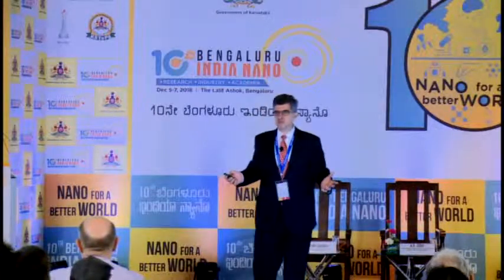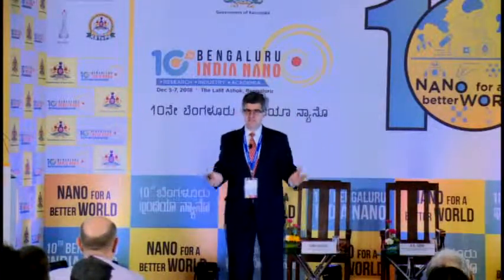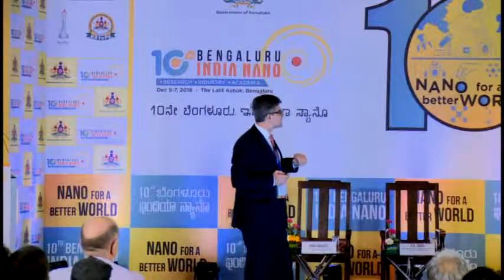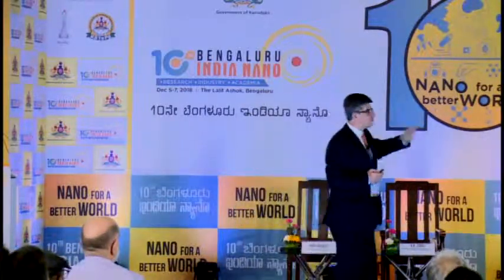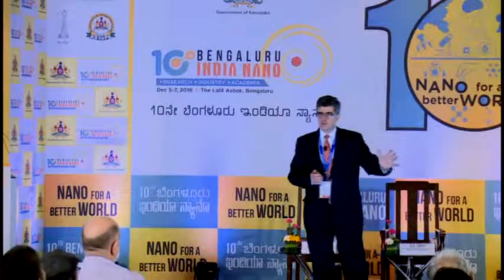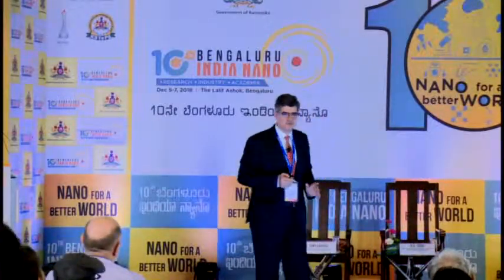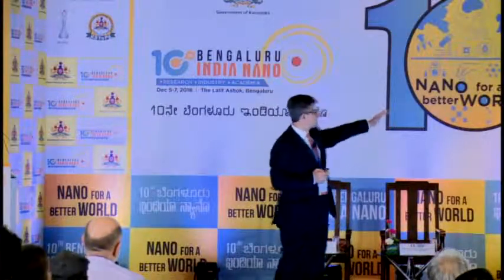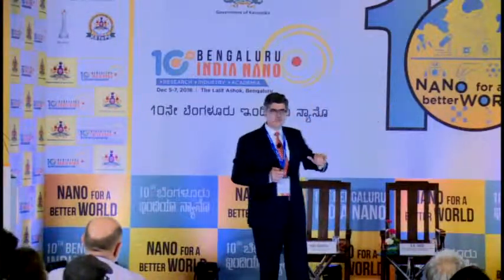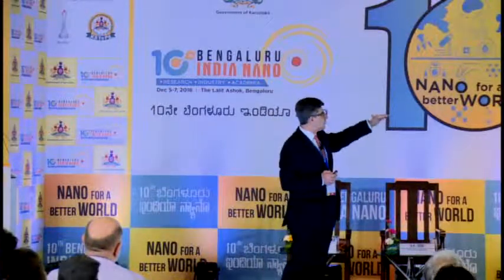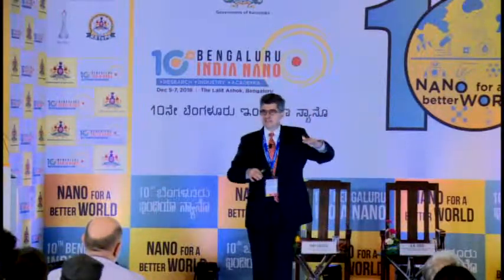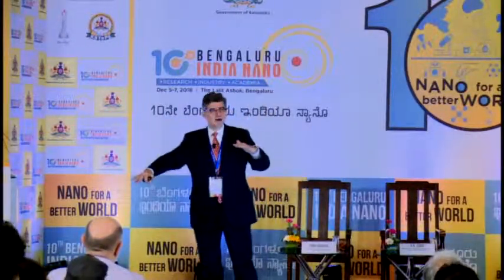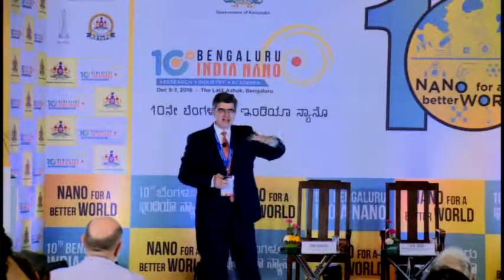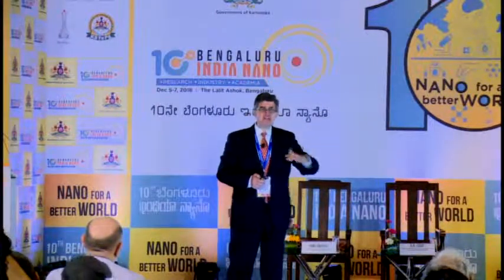Moreover, what is nice, as I mentioned already, we have lots of these materials. They can be seen like M2X structures, M3C2, M4C3, or M4N3, and we actually just added another layer of structure. But what is interesting, they can form random solid solutions, but 3 years ago, we showed that we can make ordered double transition metal MXene. So one layer surface, for example, moly, inner layer of titanium, another outer moly. So we push nanotechnology really to the limit when we align layers of atoms in the way we want here.